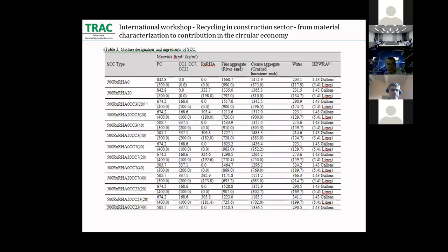Locally produced PC, Portland cement, with a specific gravity of 3.14, complies with the ASTM standard. For the chemical admixture, a high range water reducing admixture, HRWRA, with a solid concentration of 42% in accordance with ASTM C494, was used to control the slump flow of the self-compacting concrete in the range of 725 plus or minus 75 millimeters diameter. The self-compacting concrete was cured by soaking in lime saturated water at 25 Celsius until the testing time.